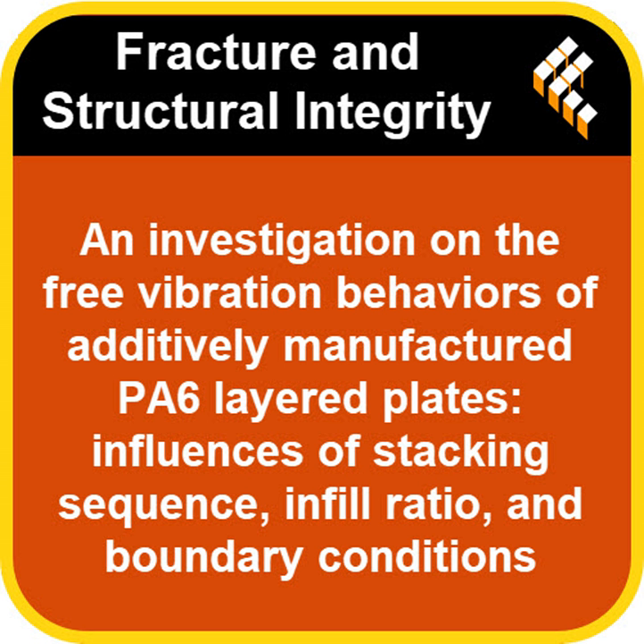Well, the stacking sequence of the infill layers, how they arranged those 40, 70, 100% layers, turned out to be incredibly influential. And in some ways, the results were quite surprising. Okay, here's where it gets really interesting. What was the big surprise? Lay it on us. All right, so the configuration that consistently produced the highest natural frequencies, it wasn't the one with the most material overall, the 100, 100, 100. It was the one with 100% infill layers on the top and bottom surfaces and only 40% infill in the core. The 100, 40, 100 configuration. That's the one.